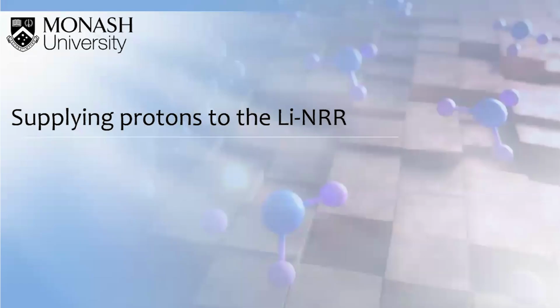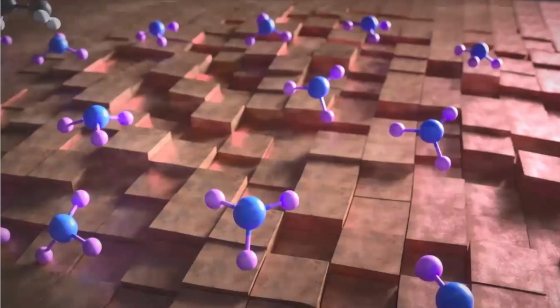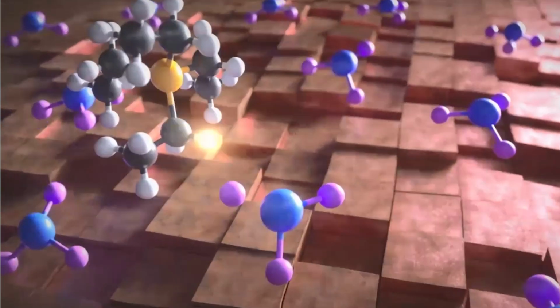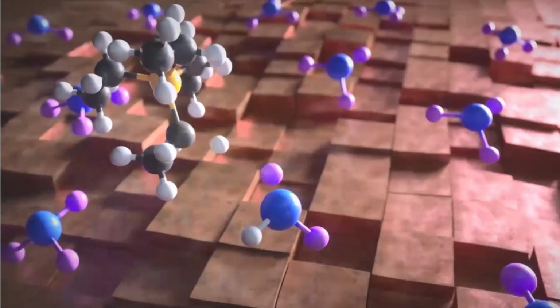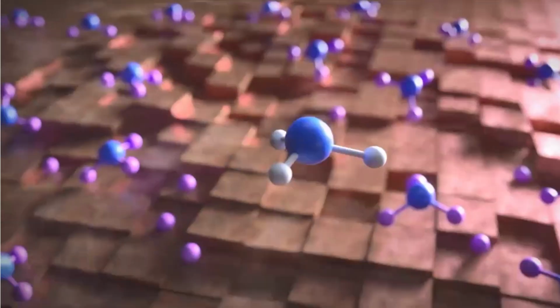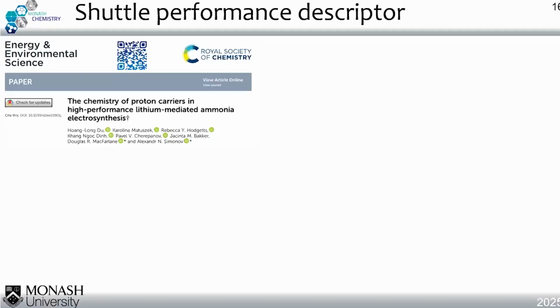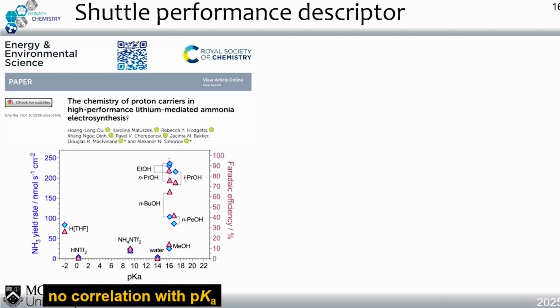So let's talk about supplying protons to the Li-NRR, because it's also very important to balance the reaction. How does the proton carrier work? It carries the proton generated from the anode and moves it to the cathode, where the lithium nitride forms, and then protonates the lithium nitride to form ammonia. We tried to understand the chemistry of proton carriers, so we came up with a list of candidates like alcohol groups, ammonium, organic acids, protonated solvents, even water and ionic liquids. We tried to correlate the pKa, the famous parameter in organic chemistry representing acidity and basicity, with the performance of ammonia, but we couldn't find a relation.